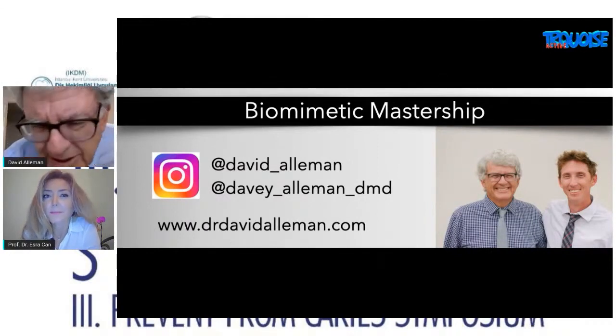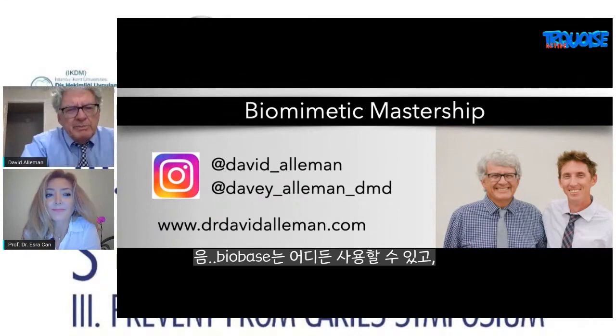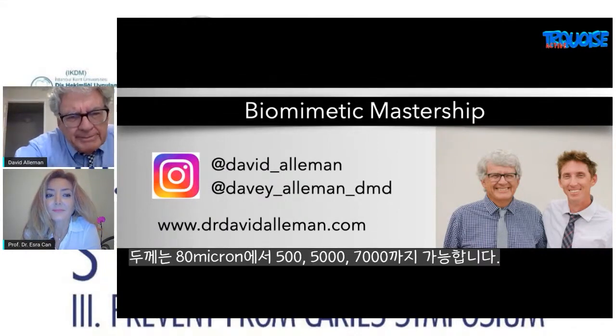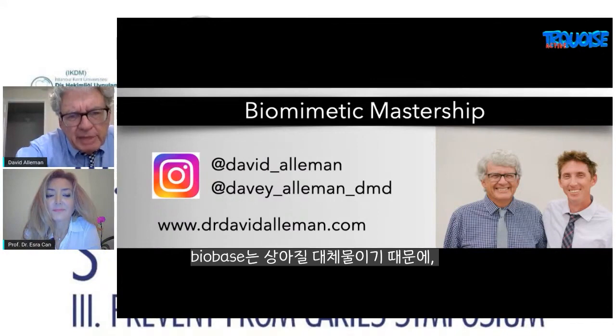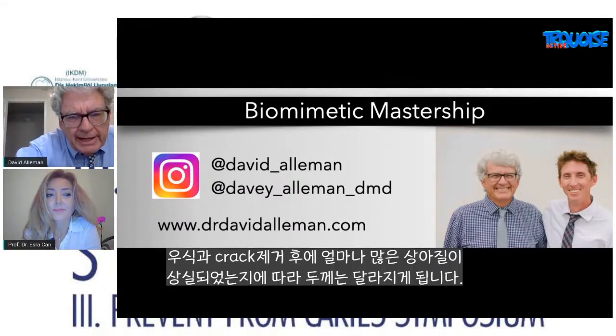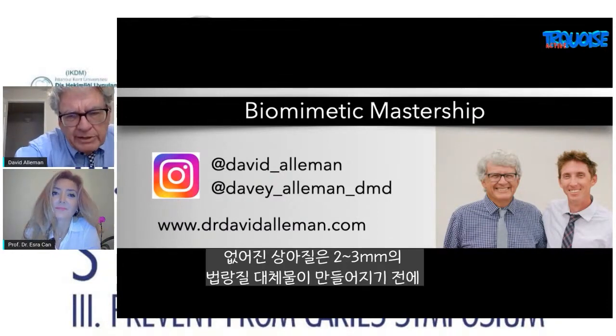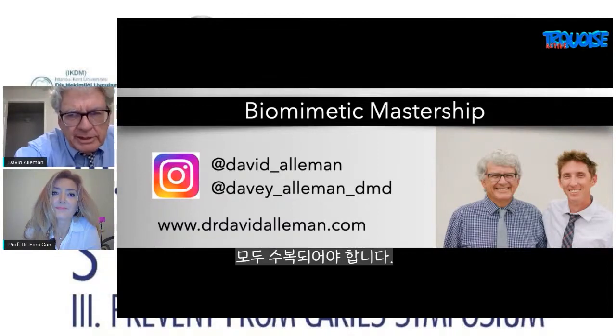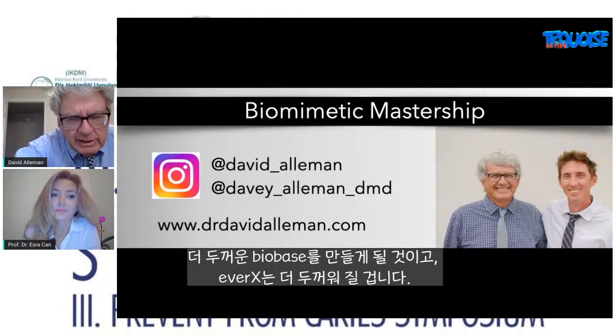Is that correct? Well, a biobase can be anywhere from 80 microns in thickness to 500 microns in thickness to 5,000 or 7,000 microns in thickness. The biobase is the dentin replacement. So it just depends on how much dentin is missing after caries removal and crack removal. And those areas that are missing should all be restored before the 2 to 3 millimeters of enamel replacement are fabricated. And so if you have a large area of dentin missing, then you would make a thicker biobase and the Everx would be thicker.